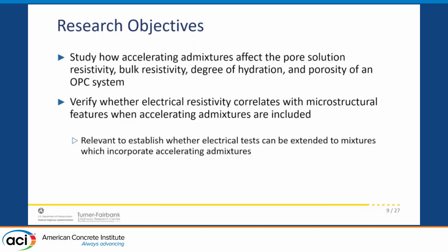So the research objectives were to look at how these admixtures can affect the electrical properties, the degree of hydration, and the microstructural features, and verify whether electrical resistivity as a test can actually capture the microstructural features of this type of concrete without being affected in one way or another from the inclusion of accelerators. This was important because we wanted to verify if we could use electrical tests for quality control and really include these type of tests into the mixture design for these applications.